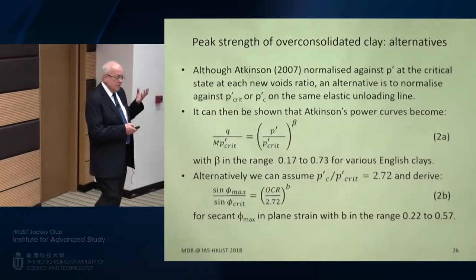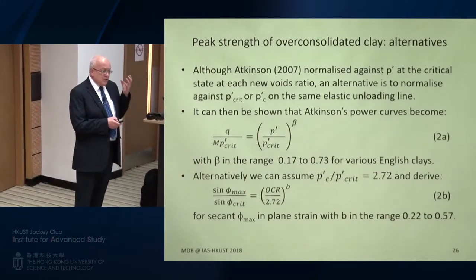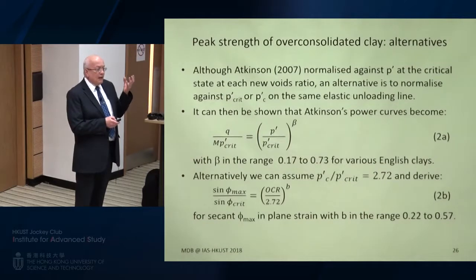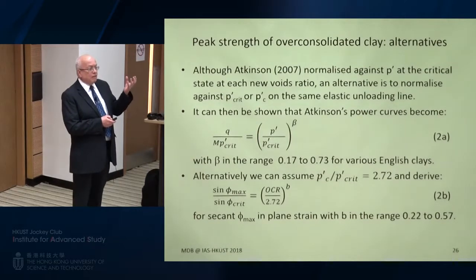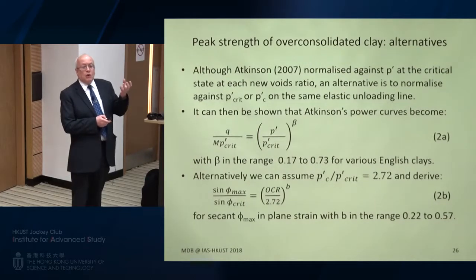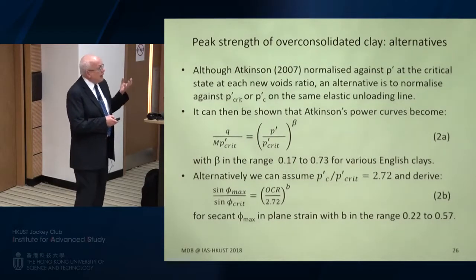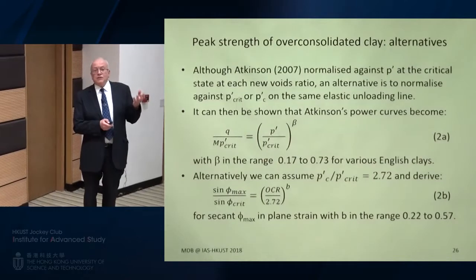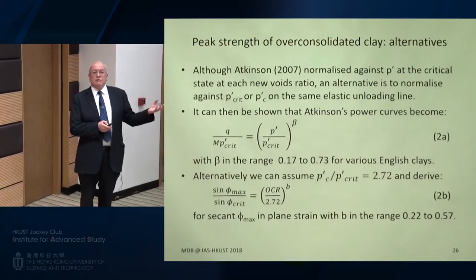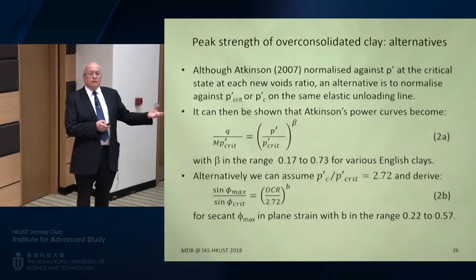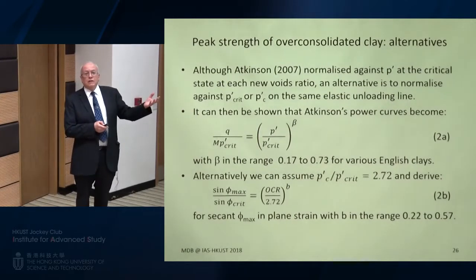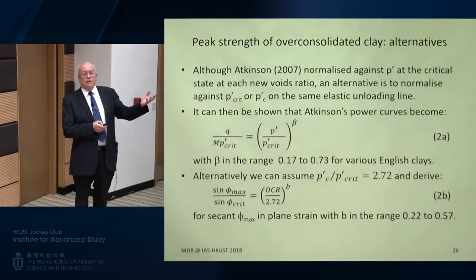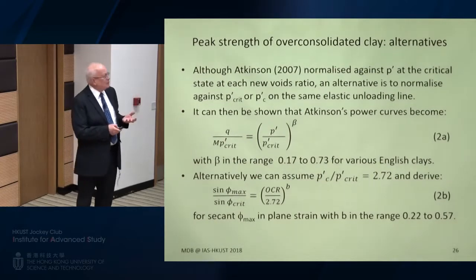Because in this case, in the sand, you had no idea what the probability of fracture of the different grains was. They'd never been to such high stress before. In the clays, everything's been taken up to a high stress because we're dealing with over-consolidation ratio. So it's actually a different stress history condition than was the case in testing sands. We don't often think of testing sands through an over-consolidation cycle. I think we probably should, but we don't.